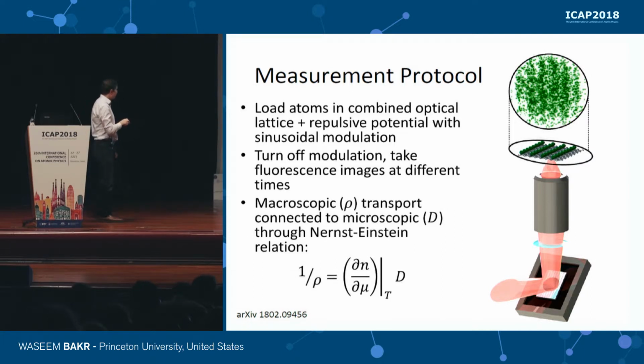And then on top of that, we add a long wavelength sinusoidal modulation that you can see even in these single shot pictures. You can see stripes along one direction. This is something we, again, send through this micromirror device, so we can control the wavelength of this sinusoidal modulation anywhere from a few sites to the full system size, which is about a diameter of 30 sites or so.